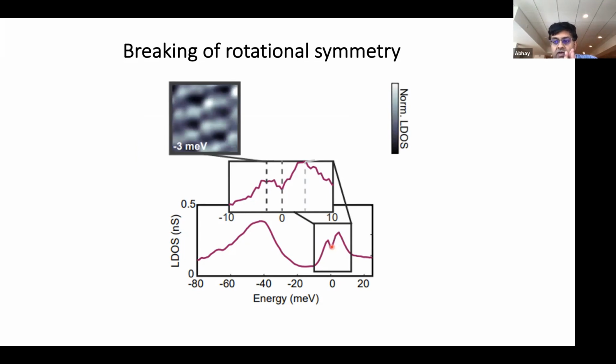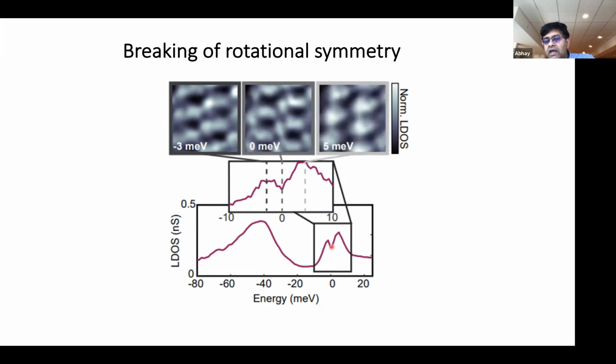Because we could see this clearly as a function of doping within the same sample, we had a good amount of confidence that this was not just coming from external strain in the sample. It's something intrinsic. It goes away when you move the doping away from that particular value. Only at this particular value do you see this threefold rotational symmetry breaking, and we saw it over a reasonably wide range of energies near the chemical potential.